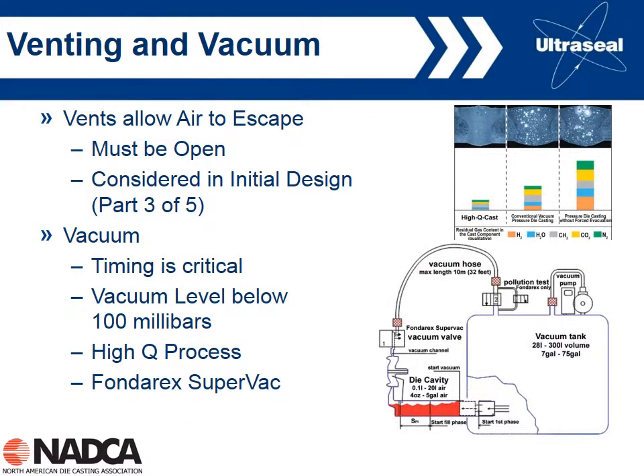Let's talk a little bit about vents and vacuum. Obviously, both can help remove air from the cavity in terms of reducing porosity. However, we obviously got to make sure that both are working well. Vents must be open. We'll talk about that a little bit later. And certainly, one of the things worth talking about is this new high vacuum process. This is where you get very low levels of vacuum, 100 millibars, maybe even 50 millibars, which is actually quite challenging to get in a die casting die. So some of these new high vacuum systems, such as a high Q process, the Fondarex SuperVac process, enable you to get very low levels of vacuum, but you have to have a specially designed die to do that.